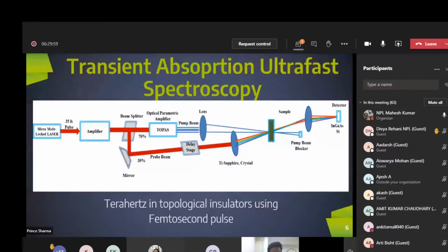In my experiment, we detect the terahertz in TI using transient absorption ultrafast spectroscopy, in which the TI, placed in the place of a sample, is excited by 650 nanometer with an average power of 1 milliwatt. The kinetic profile which comes out through this experiment is considered, which shows oscillation in the 1 picosecond to 10 picosecond range.